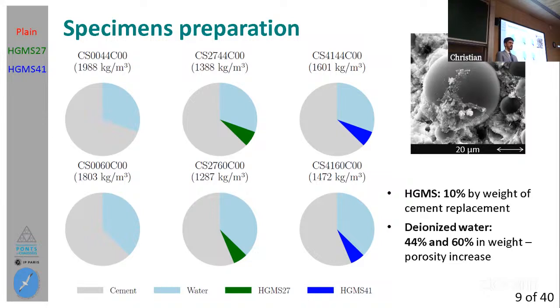Totally true. Yeah. Well, what I can say there is that during this slurry state, I mean the first state of the cement, there will be no consumption of this outer glass shell and all that. So we can trust the results that we obtained through MIP on the powder samples. At the beginning, yeah, that's it. So if we don't get to pressures close to those at which the spheres start to break, then we'll be okay. The spheres will still be there while in the first state of the cement paste, the cement slurry actually. Well, then the cement will harden, and we'll have to see there what are the conditions of pressure mainly that will possibly break the spheres as time passes by due to the consumption of the outer shell.